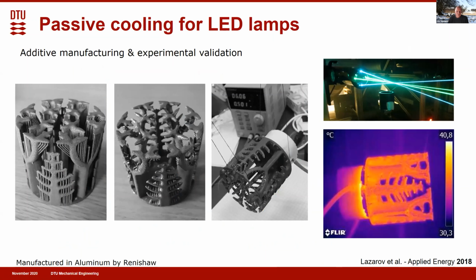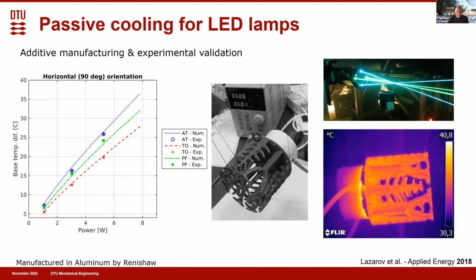And so in collaboration with Renishaw, we also got some of these structures manufactured. So they were 3D printed in aluminum. For these early devices, we didn't take overhang into account. So there was quite a job in removing overhang. But then when the structure was cleaned, it fitted very well with the numerical expectations. And we could show that we were significantly better than the designer's best choice and a pin fin structure, and then this topology optimized structure.